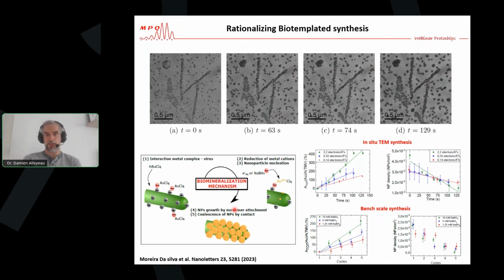And as the density is already very high, we also have a lot of coalescence. And that's what you want to avoid if you want to increase the density. So we did an experiment where, by increasing the dose rate, we see that we increase the growth rate of nanoparticles at the surface of the virus. And we compare this result with a bench scale synthesis where we use NaBH4 to reduce the metallic precursors, and we do that through different reduction cycles. And we observe the result of the synthesis at each cycle. And you see that when you increase the concentration of reducing agent, you increase the growth rate of the nanoparticles at the surface of the virus.